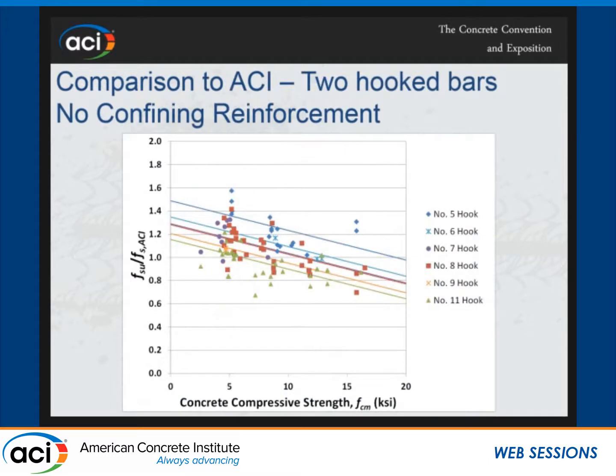This is a comparison with the ACI — what you would get in an ACI prediction for bond stress. This is the ratio of the stress in the bar in test to that predicted by the ACI versus concrete compressive strength. These are for specimens with just two hook bars — we had two, three, four, and six hook bars in our specimens. Why compare with two hook bars? Because this is the basis for the current ACI code: all the original tests in the 1970s were based on two hook bars. You can see, starting at number 5 bar, then 6, 7, 8, 9, and 11, in that order, that we're probably using longer development lengths than we need for small bars in low-strength concrete, and not enough for the larger bars — number 11 bars are below 1.0 average.